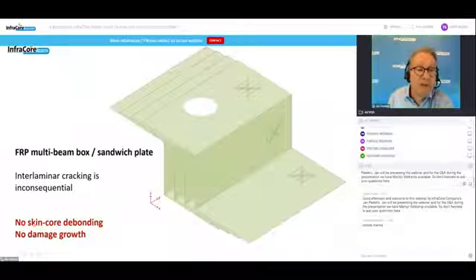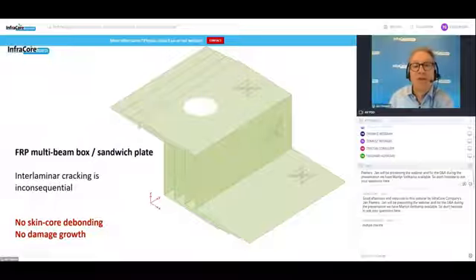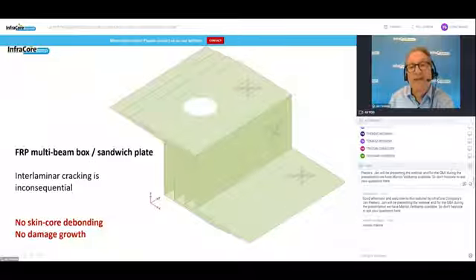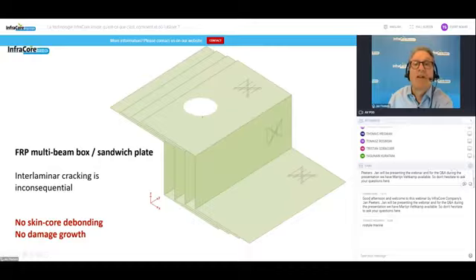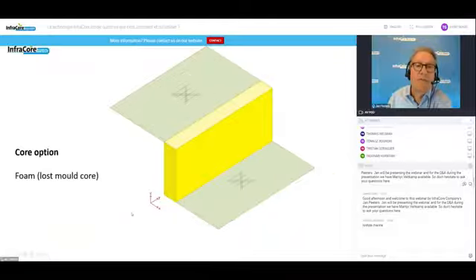So we do not get a skin core debonding because the connection to the core remains intact, even if you damage the interface a little bit here by an indentation. The interface essentially stays intact. You cannot take away material from the top, and you have no damage growth.